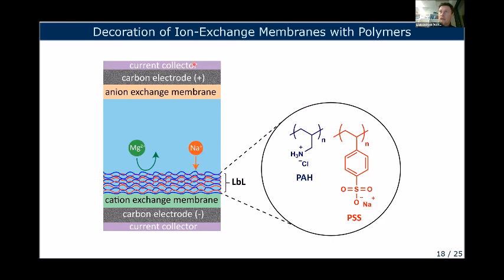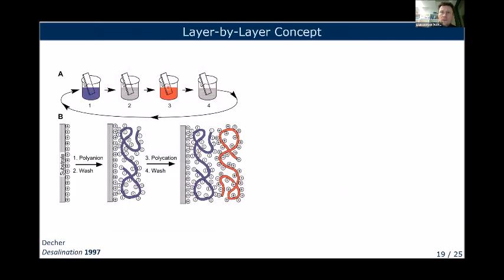So the transport, again, of course, is driven by the electrical field. And due to the electrostatics being present in these layers, divalent is rejected and sodium can go through. That's not the case for all combinations of polymers and conditions, but there are parts in that window that would fit with this cartoon here, as I will show you in a minute. So it was Gero Decher already in the late 1990s who started reporting on these.